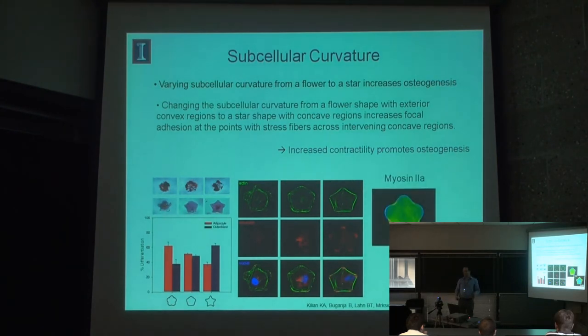One thing that's really terrific about doing these patterned cultures is that when you have unpatterned cells, they're all over the place. Every cell has a different shape. It's really tough to make any morphological conclusions about them. But when you do patterning, you're constraining every cell in the same geometry, so you can do cool things like make heat maps. What these are is we took 80 and 86 images of single cells that were stained for myosin 2A, and then overlaid them in ImageJ, a program you get from the NIH, and then you can generate an average immunofluorescence heat map, which can give you a semi-quantitative indication of a feature.